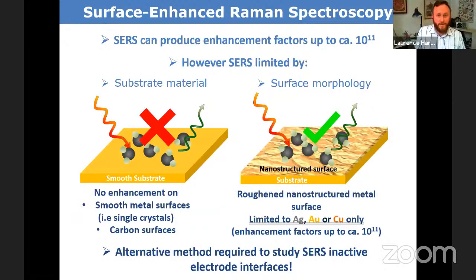So surface enhanced Raman spectroscopy has been around since the 1970s, when it was first reported. And you can enhance the Raman signal by, in very idealistic cases, up to 10 to the 11. So huge amounts of enhancement. However, SERS is limited by the substrate material. Only certain materials can give a surface plasmon to give the enhancement, such as these nanostructured surfaces, and there you're limited to silver, gold, or copper.